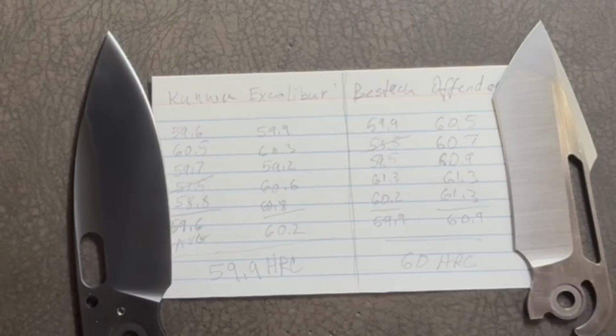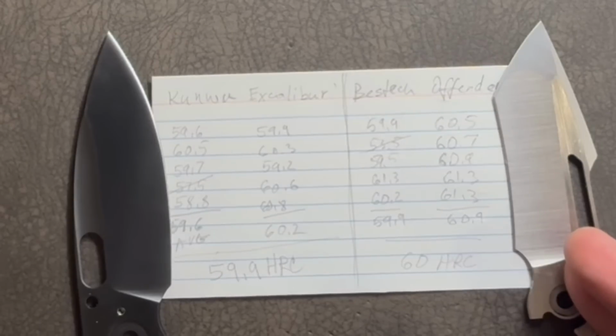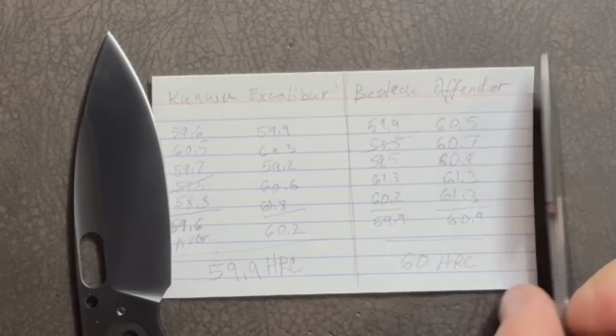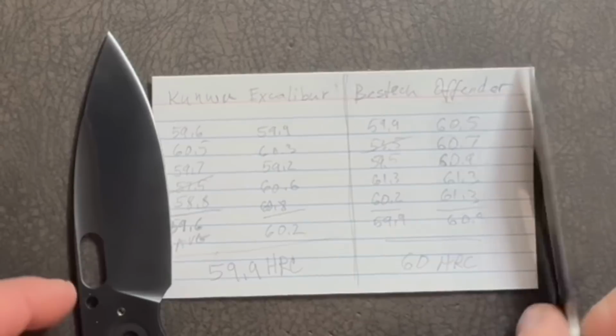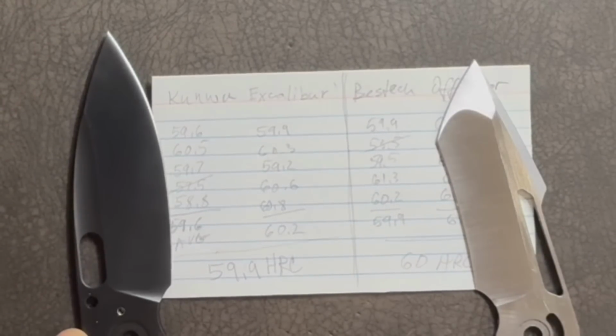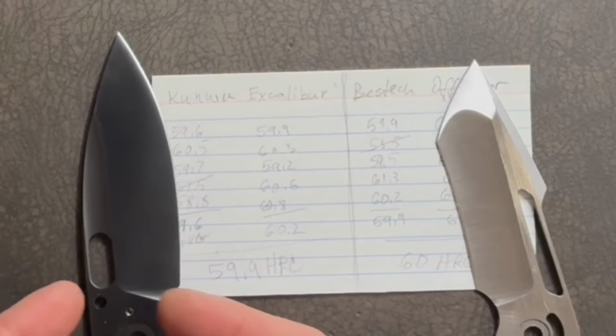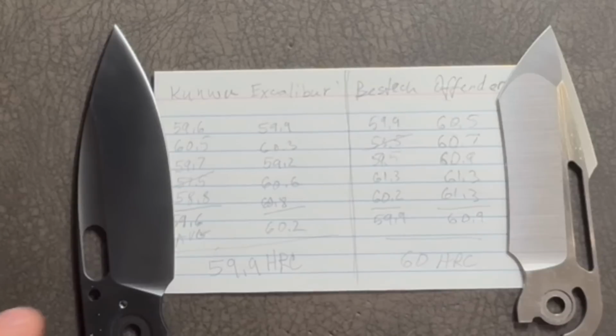The difference is this was advertised 63 to 64 because it's made of MagnaCut, and this one was advertised 60 to 61 because it's made out of Vanax. Okay, so enough about that. Let me show you what the Rockwell readings are for these knives, and then if you stick around just a little longer after that, I will investigate the reason why Leeb gives incorrect information in some cases.